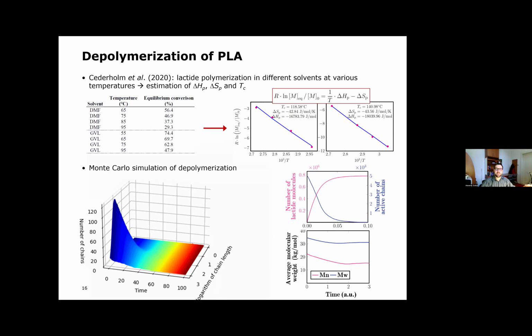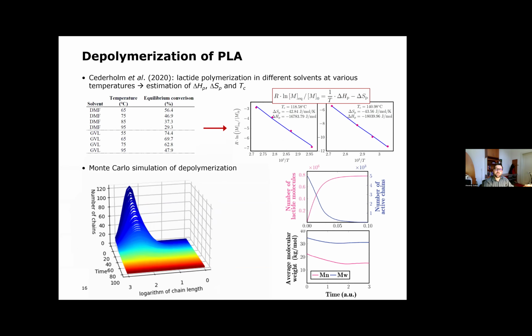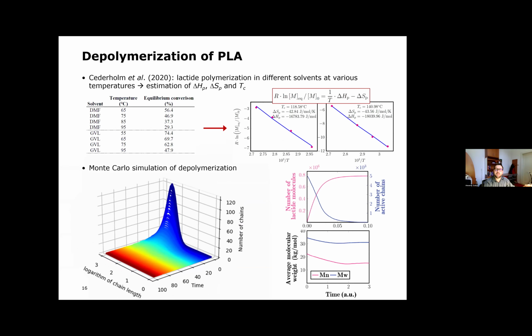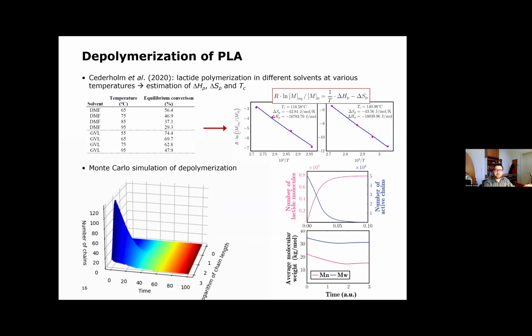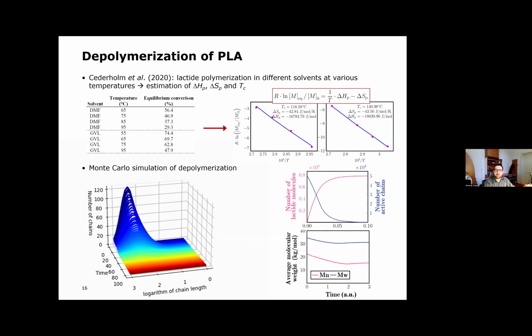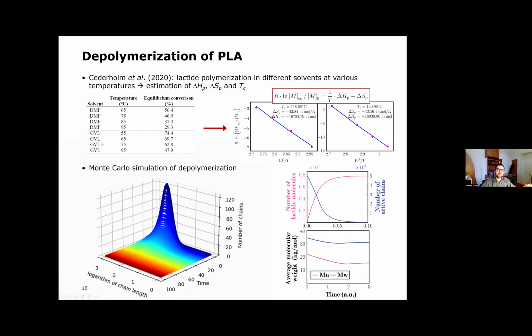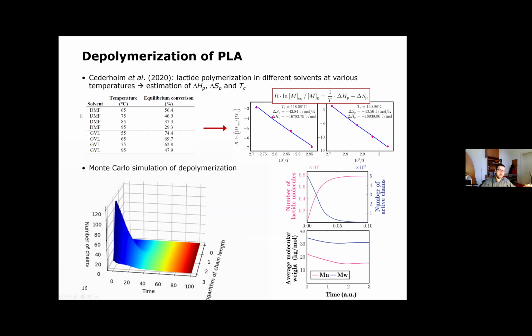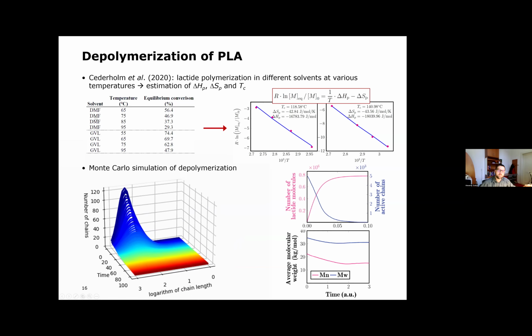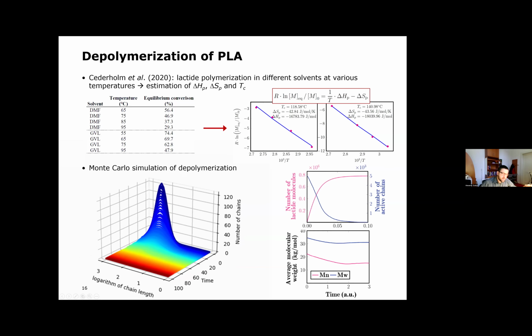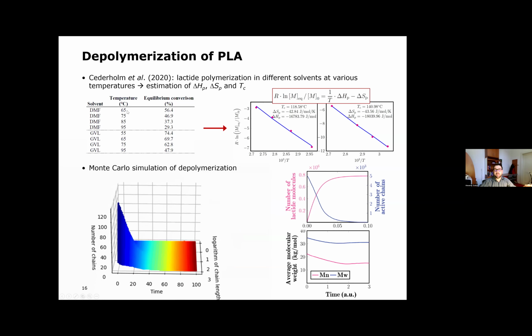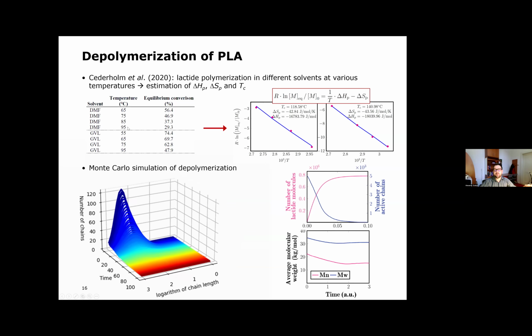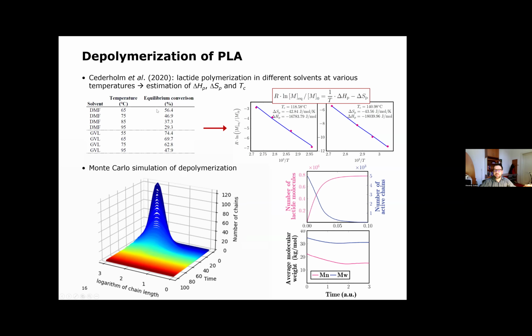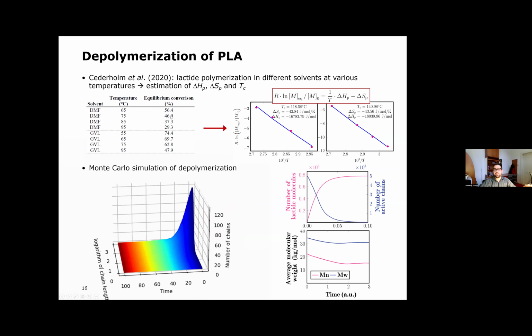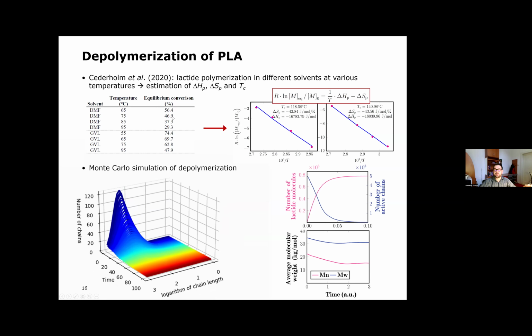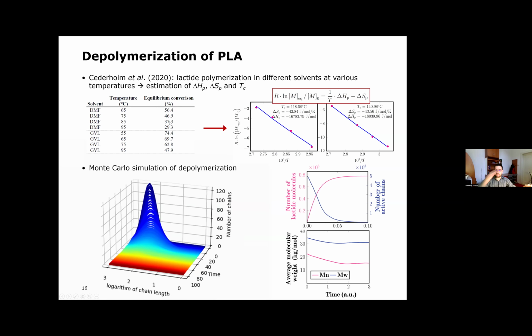but that is still rather in the field of ideas than reality. In the paper that I just talked about, they carried out lactide polymerization in different solvents at different temperatures. So for instance, here in the table, you see the solvent DMF, which is dimethylformamide, if I'm not mistaken, and GVL is gamma-valerolactone. And you see that with increasing temperature, they are getting closer and closer to the ceiling temperature, and their equilibrium conversion is actually getting smaller and smaller.